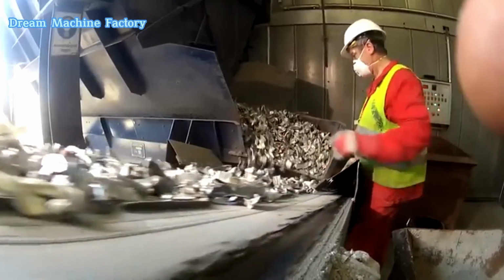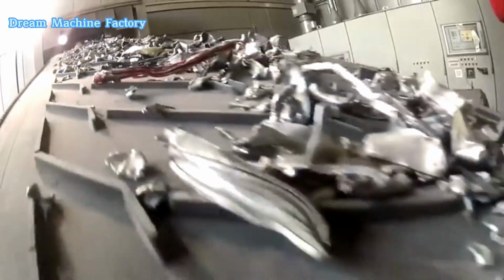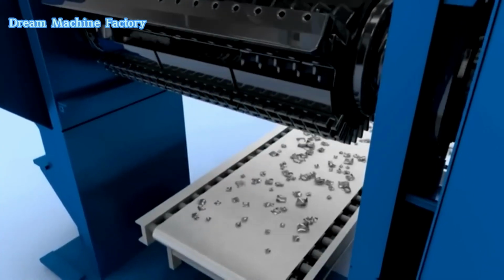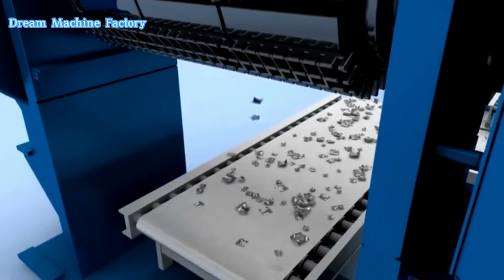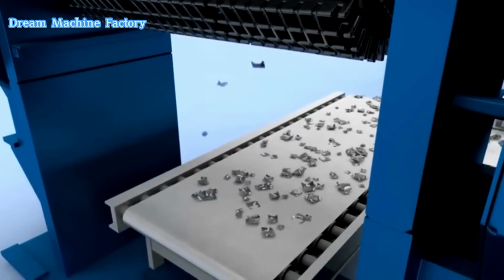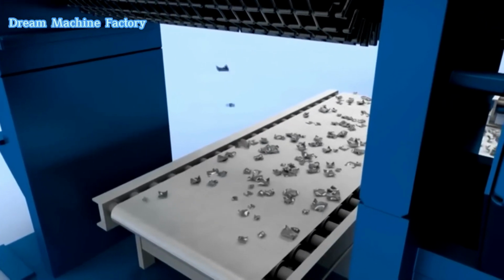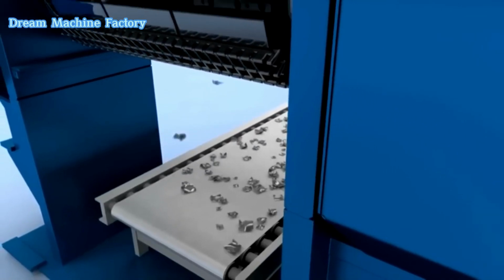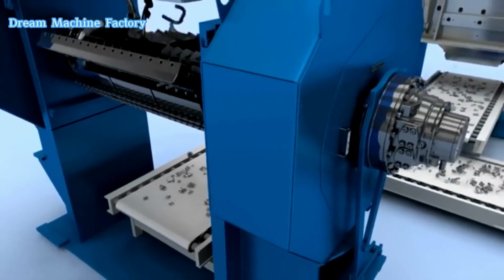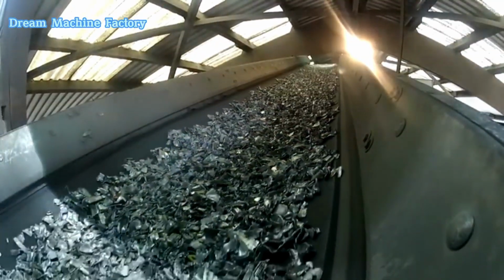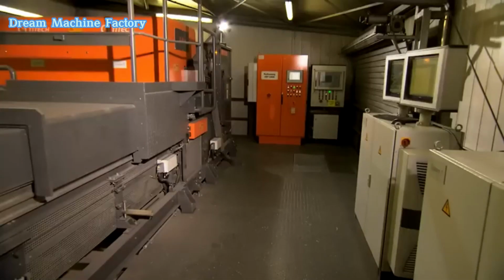Refining aluminium scrap. Even within aluminium scrap, there are different alloys. For instance, aluminium window handles and rivets often contain heavy metals such as copper and zinc, which are unsuitable for window frame production. To remove these impurities, a special X-ray transmission machine is used. The machine scans the shredded aluminium pieces and identifies unsuitable alloys. The identified unsuitable alloys are then removed using a system of high-speed air jets, capable of analyzing and sorting 1,000 parts per second.